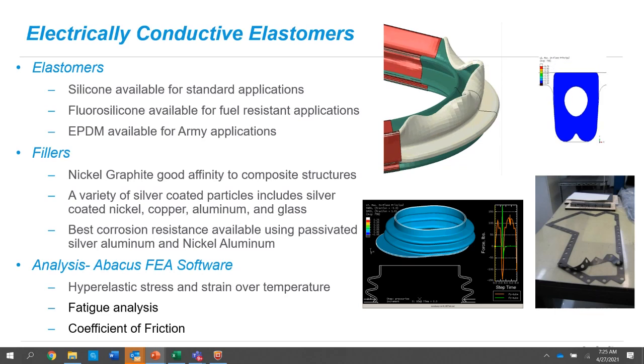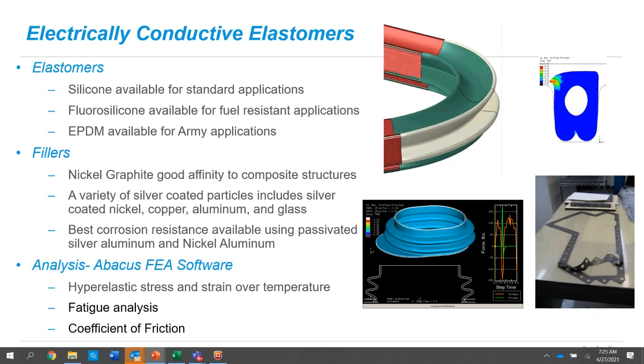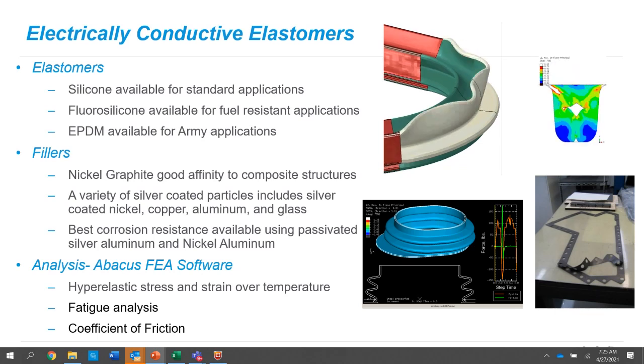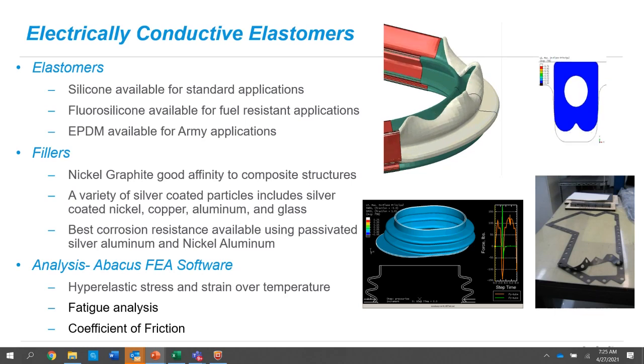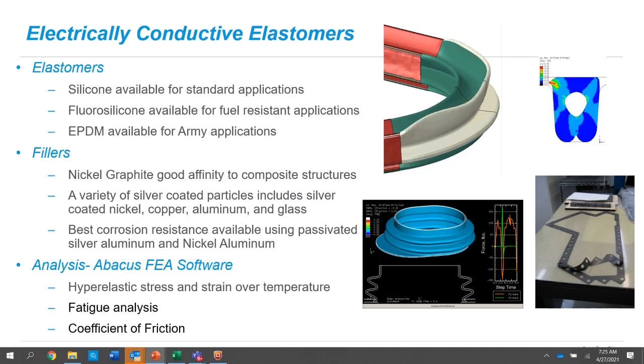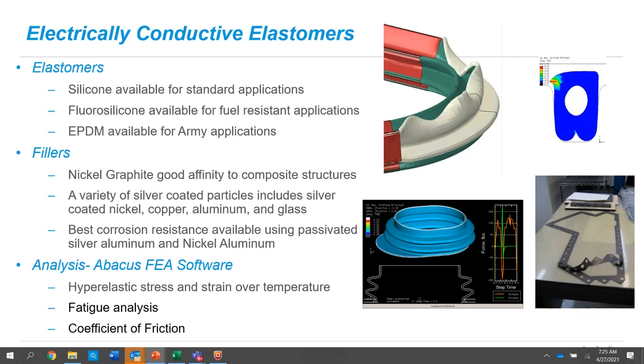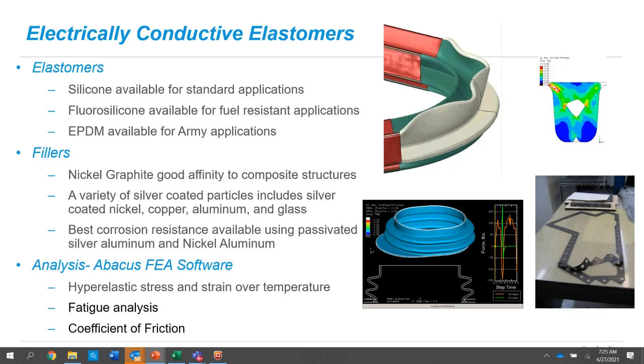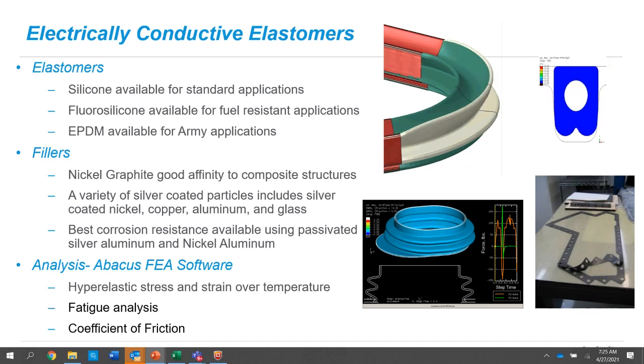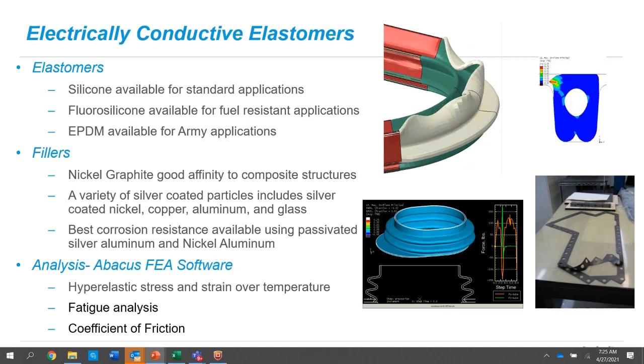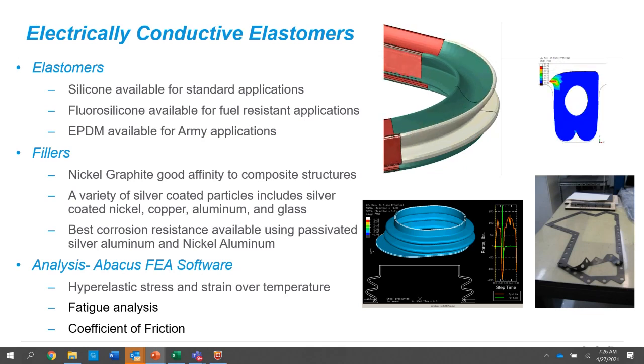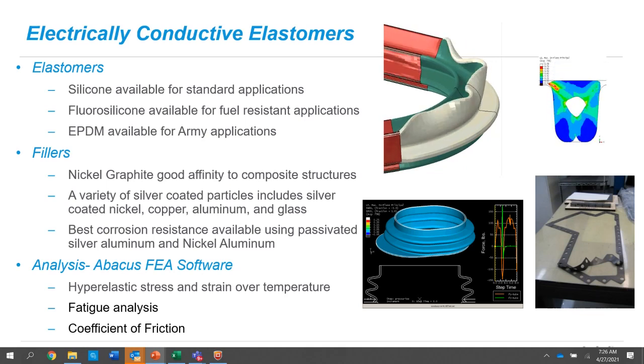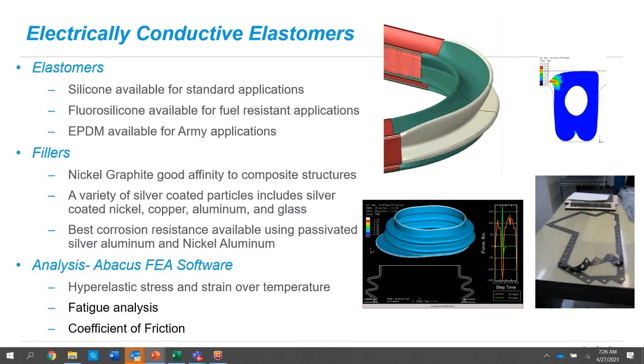So we have silver coated nickel, copper, aluminum, and glass, and I touted the silver coated aluminum. That's probably the one that we sell the most of because of so many aluminum housings that are being used. And then we just came up with two new corrosion resistant materials, which include a passivated silver aluminum and a nickel aluminum. And the nickel aluminum is probably the best for corrosion resistance.